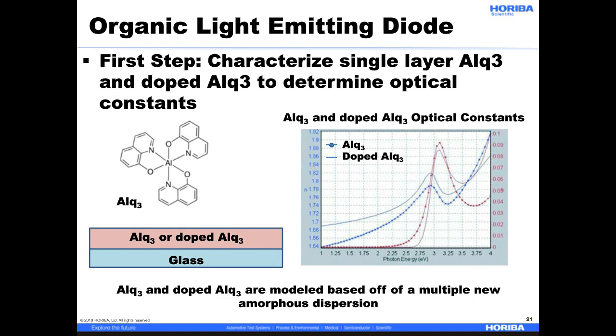So what we're going to go through here is how to actually characterize this full device, and we're going to do it step by step. For SE analysis of multi-layered structures, it's helpful to have each component of the device as a single layer, preferably a bulk layer, to first obtain the optical properties for each material. This gives you a starting point for each material so that your correlations are reduced when you're trying to fit 5 or 6 layers.